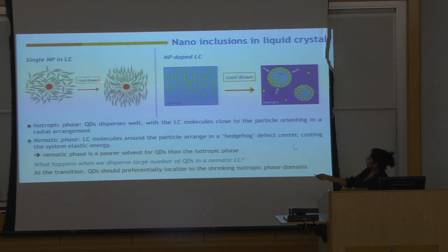When we cool down and these molecules are trying to orient in some particular direction, these ones can't. They are still interacting with the ligand molecules. This is called a hedgehog defect. And every defect costs energy. So the liquid crystal is really unhappy when we put nanoparticles in there when it's in this nematic phase. So if we put a whole bunch of them and we cool down, instead of each of them forming tiny hedgehog defects everywhere, the liquid crystal pushes the nanoparticles into these regions so that there can be fewer, larger defects, but fewer. So fewer is better. That's a lower energy cost.